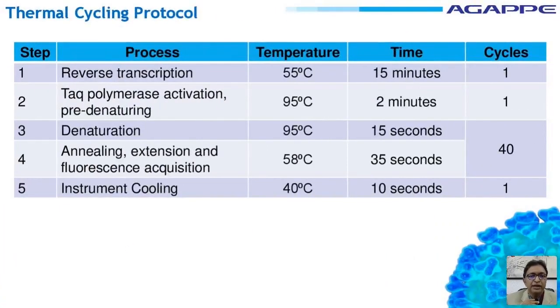Now, these are the recommended thermal cycling protocols for the kit. As I mentioned in the beginning, the reverse transcription is done at 55 degrees for 15 minutes, and then you have 40 cycles consisting of denaturation for 15 seconds, then annealing and extension, which is done at 58 degrees for 35 seconds. These are repeated for 40 cycles, and at the end of the 40 cycles, you also cool the instrument to 40 degrees for about 10 seconds.